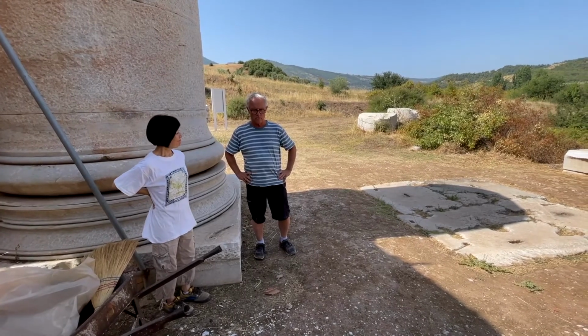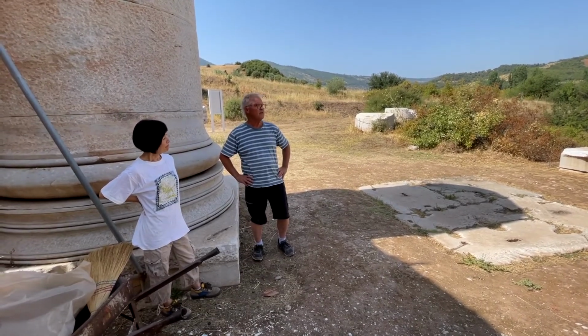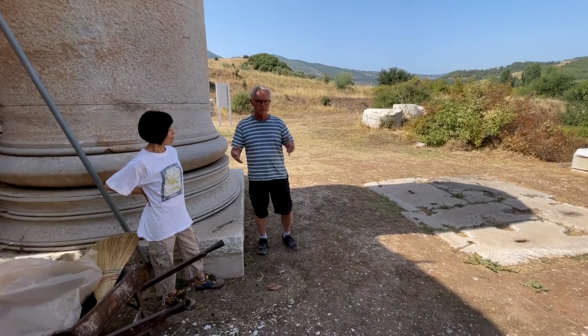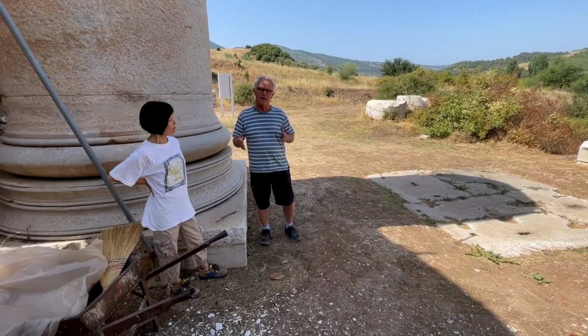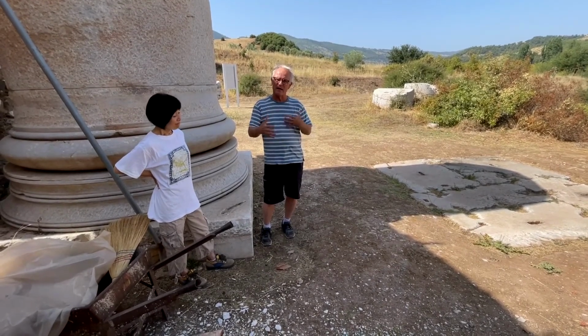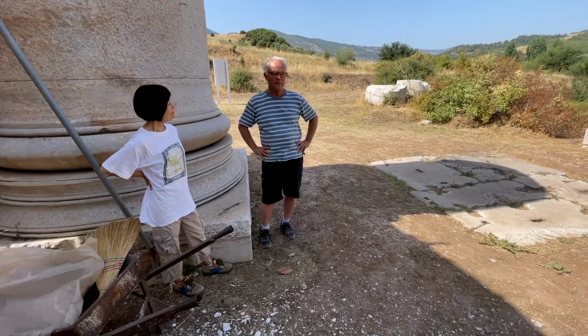And we used an army of women from the village to apply the biocide. The method was slightly different. We chose to use a lower concentration, but the duration of the biocide would be over 5 days. So it was really a time, allowing the biocide to just sit in the stone and get into the interstices of the marble. And that seemed to work.